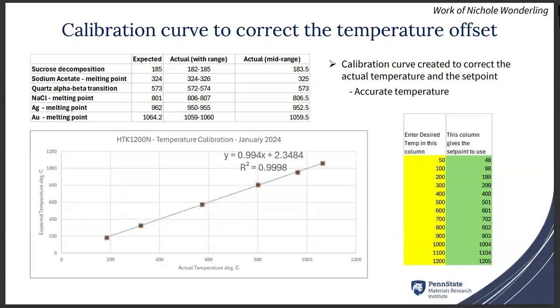And so by doing this experiment with all these different standards, we can compare the expected temperature with the mid-range of the actual value we got using our experiment, leading to a calibration curve that can be fitted and used in order to correct for the temperature deviation.